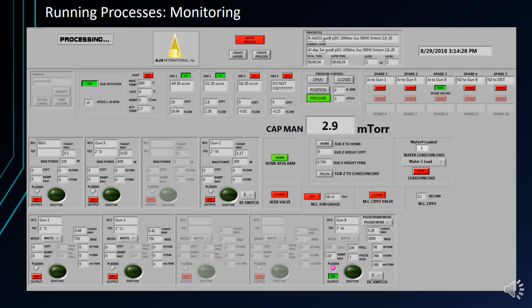Since I wrote this process, I am expecting this layer to bring the power to 300 watts. Then it will sit there for a 300-second pre-sputter before the shutter opens for a 1,000-second long coating. The shutter will then close. The gun will ramp down over 180 seconds to 30 watts, and then the process will end and turn off the power to the gun, the gas flows, and open the main chamber turbo completely.